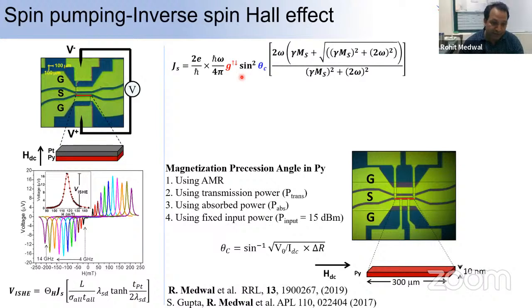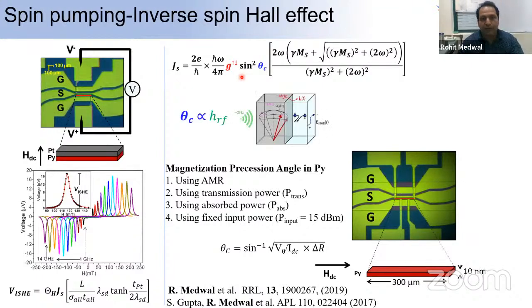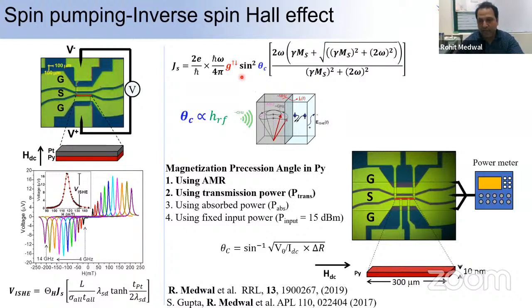These two factors are very important, and we tried to find out the main reasons for the accurate estimation of the precession cone angle, or you can say the estimation accuracy of the spin Hall effect in platinum using this method. We try to find the precession cone angle by four different means: using the AMR, using the power transmission, using the power absorption, and using the fixed input power.